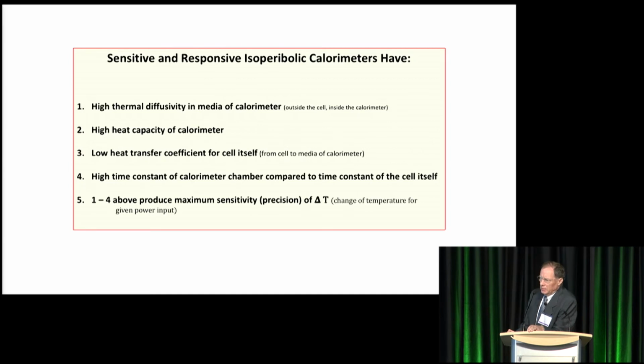To get a good calorimetry, I thought that you would need high thermal diffusivity in the calorimeter media, that's outside the cell. You need high heat capacity of the calorimetry, but not of the cell itself. You need a low heat transfer coefficient for the cell so that you can amplify the delta T signal, and the time constant of the calorimetry chamber needs to be much larger than that of the cell.